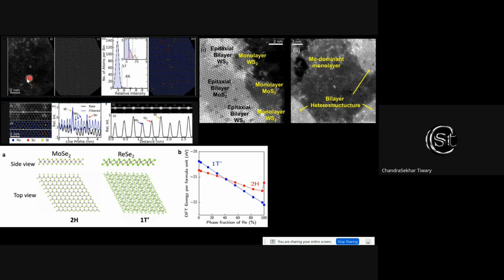So, for example, this is MoS2, WS2 structure doped with tin. Now, wherever there is a bright spot, that is tin, which clearly shows that by just replacing one or two atoms, we can make different morphology or a different structure. The stacking of layers changes. Also, phase transformation is possible by just doping a small